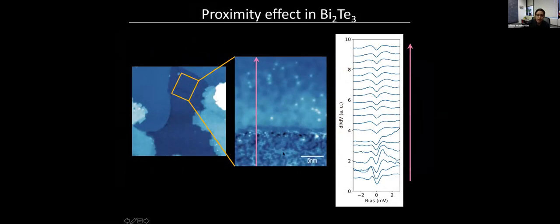You can see this proximity effect. The proximity effect is really interesting. This is bismuth telluride, and what you see is a shallow gap on bismuth telluride. Remember, this is a lateral proximity effect, so one imagines that only the surface state is getting proximitized. The gap magnitude is also pretty small compared to the gap magnitude on FeSeTe.